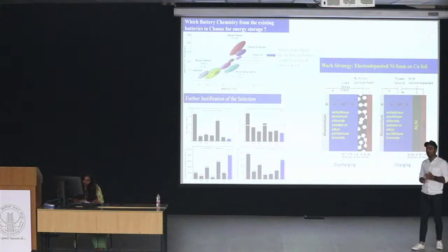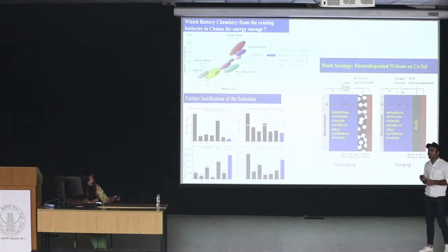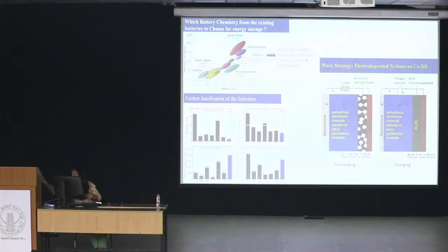Some researchers have already worked on aluminum-ion batteries, but the cycle life does not go beyond 100 cycles. So here we come with our new approach, the aluminum intermetallic battery. We are using aluminum as an anode and nickel foam as a cathode. During discharging, aluminum is oxidized to Al3+ and forms an intermetallic with nickel. During charging, it breaks the intermetallic and returns pure aluminum. We are also using an ionic liquid, which is itself an ionic compound containing aluminum ions, helpful in forming the aluminum-nickel intermetallic. Our battery is environment friendly, earth abundant, non-flammable, and good for a cleaner and greener tomorrow. Thank you.